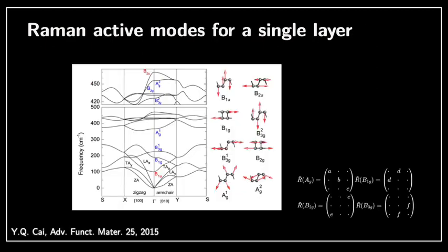So this is a typical spectrum. Actually, it's not a spectrum. This is the phonon band structure. It's a little bit complicated. We are not going to worry too much about it because remember, as I mentioned at the end of the last screencast, if we look only at one phonon process, we need to have a negligible transfer of momentum. In other words, only those vibrations that have zero momentum will participate in first order Raman spectroscopy.